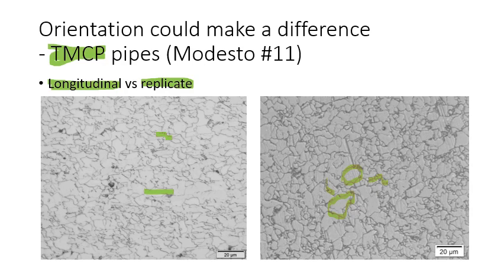I believe this effect is due to something in thermomechanical controlled processing that they call the forming of pancake-shaped grains. Those pancake-shaped grains and that plate-shaped orientation are going to look like an elongated grain in the longitudinal microstructure, but in the replica microstructure, looking down on the surface, it's going to look more like looking down on the surface of a pancake. It's going to look enlarged in multiple dimensions.